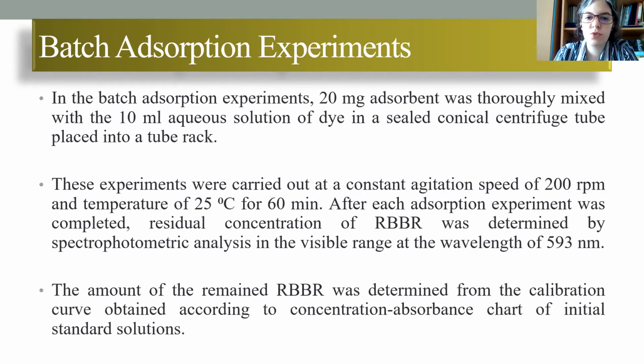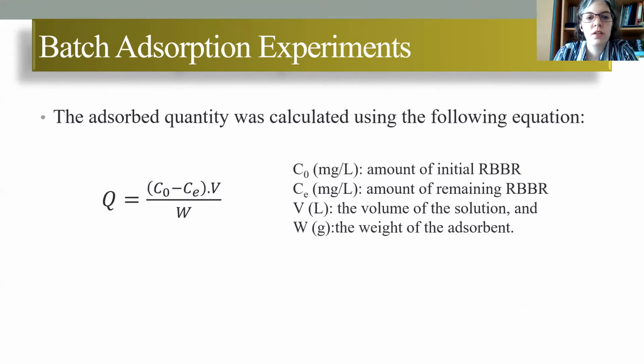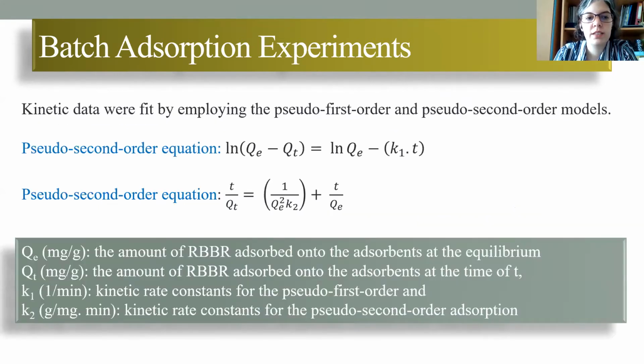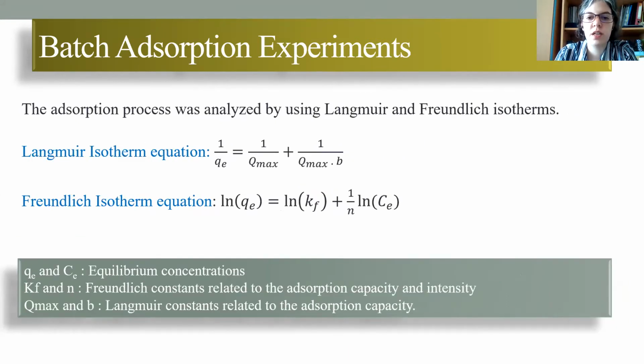In the batch adsorption experiments, 20 mg adsorbent was thoroughly mixed with 10 ml aqueous solution of dye in a sealed conical centrifuge tube placed into a tube rack. These experiments were carried out at a constant agitation speed of 200 rpm and a temperature of 25 degrees Celsius for 60 minutes. After each experiment, the residual concentration of dye was determined spectrophotometrically. The amount of remaining dye was determined from the calibration curve. The adsorbed quantity was calculated using the following equation, and kinetic data were fit using the pseudo first order and pseudo second order models. Also, the adsorption process was analyzed using Langmuir and Freundlich isotherms.